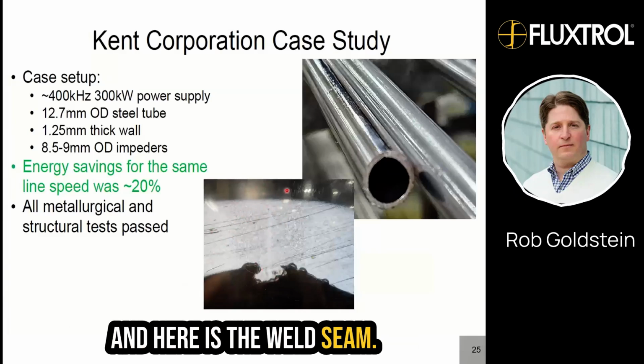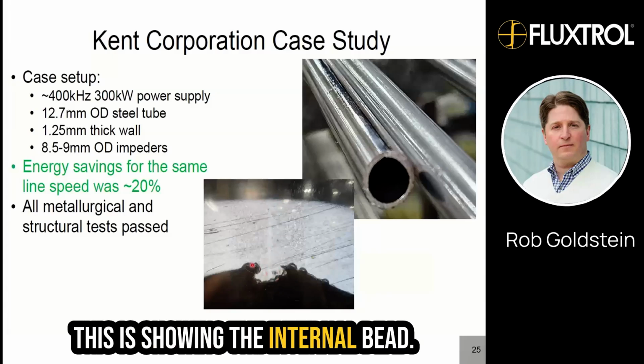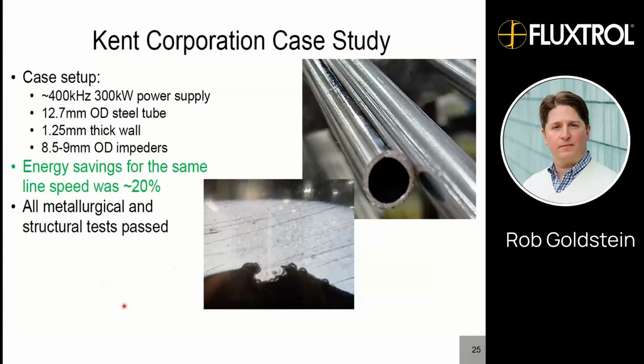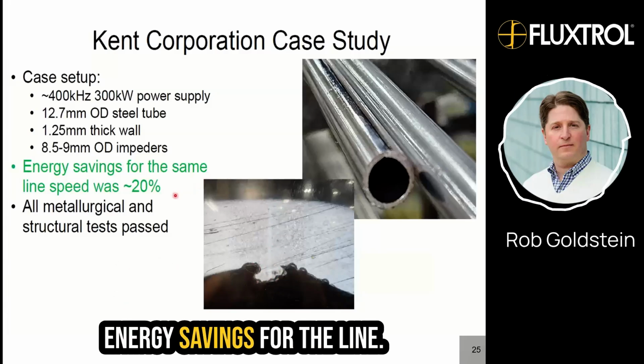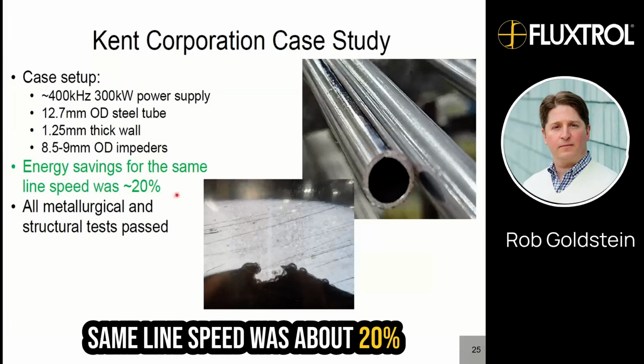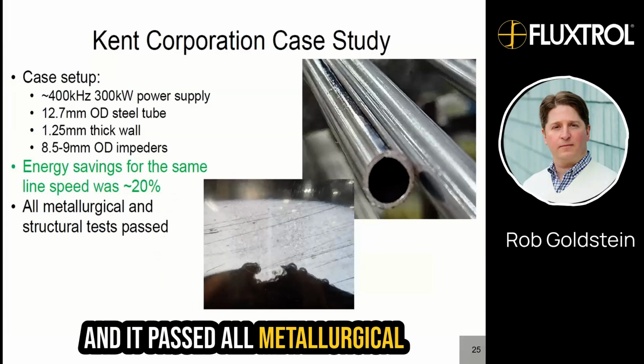This one, I took a picture of the cut part showing you the virgin material, the heat affected zone, and here is the weld seam. The external bead's been removed. This is showing the internal bead. In this case, the energy savings for the same line speed was about 20%. And it passed all metallurgical and structural tests.